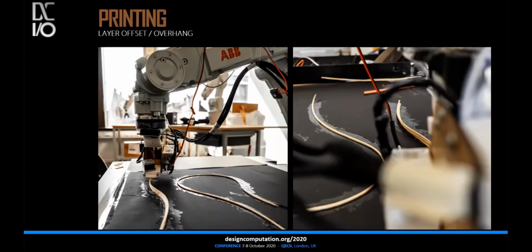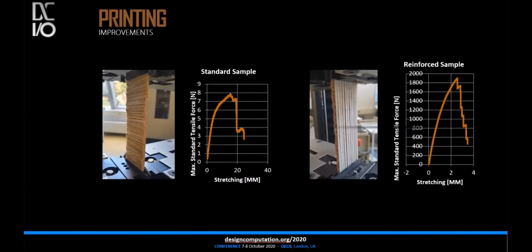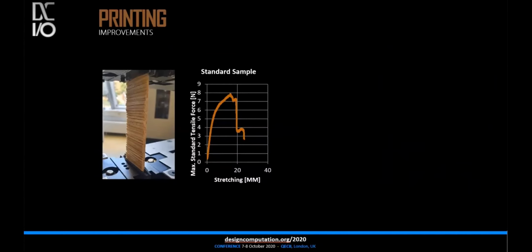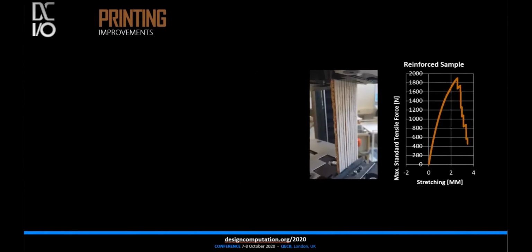To forestall and address arising questions about a possible use case, we first have to look at the performance between the layers. Samples of 15 cm in height, or 50 layers, and 4 cm in width were tested for their tensile strength against the fiber and layer direction. Without the reinforcement layer, the layer adhesion is only as strong as the adhesion strength of the used compound. With an additional reinforcement layer, the part can withstand a maximal standard tensile force of 1900 Newton.